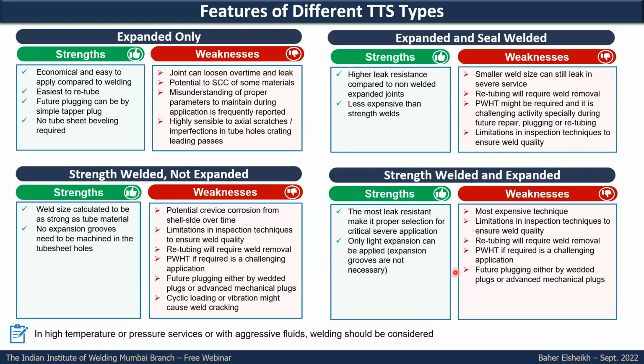You will eliminate, to a very good extent, the susceptibility to crevice corrosion, and the weakness is that it is a little bit more intensive work, so cost-wise it is higher, and there is a limitation on the inspection, as we said earlier. And again, all the requirements for the welding here, for the future plugging, post-heat treatment if required, where you need to remove the weld or apply weld again, or the application of the post-heat treatment at site, which is a